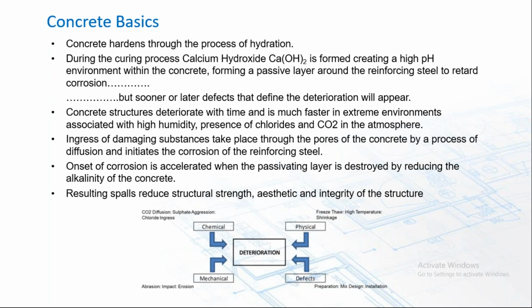Ingress of damaging substances takes place through the pores of the concrete by the process of diffusion, and that really starts to initiate the corrosion of the reinforcing steel. Onset of corrosion of the steel is accelerated when that high pH condition, or that passivating layer around the reinforcing, is destroyed by reducing the alkalinity within the concrete matrix itself. So then the steel corrodes, which creates a concrete spall, and that ultimately reduces the strength, aesthetics, and integrity of the structure. So that's pretty much it in a nutshell.